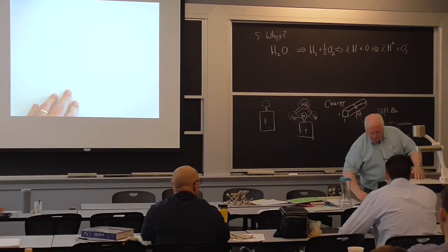So it turns out, even though it's got carbon, manganese, sulfur, silicon, phosphorus, it also has residual small amounts, unintentional amounts of nickel, might be 0.15% nickel, it could have 0.08% copper, okay, it has a couple of other things. Let's say it has 10 different elements. I can go to this thing, which gives me the composition variation of various steels. And so if I know the statistical variation of the composition that's produced on thousands of feet of steel, and I do a chemical analysis on that piece of steel, I can then do statistics to see. It's a fingerprint. And if I have a 90% confidence level, statistically, that it meets the carbon requirement,